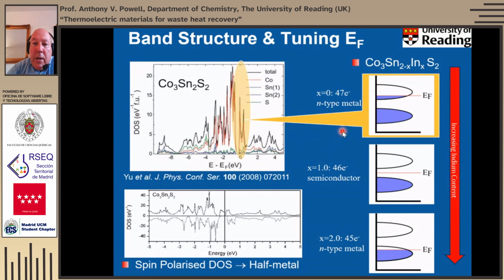And in fact, we can go, if we use something like indium, for instance, which each time we put an indium in, it removes an electron, we can go from a 47 electron material to a 45 electron material. And at the midpoint where we have a 50-50 tin-indium mixture, it's a semiconductor because the upper band is empty, the lower band is filled. And then if we go further, we start depopulating this lower band again.